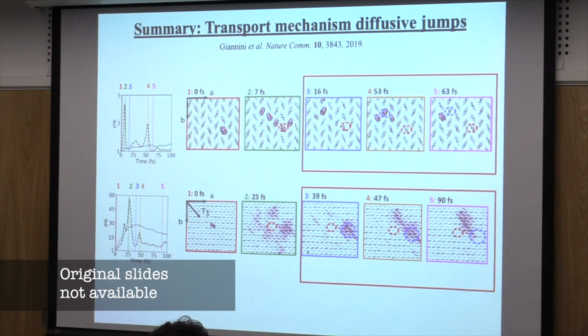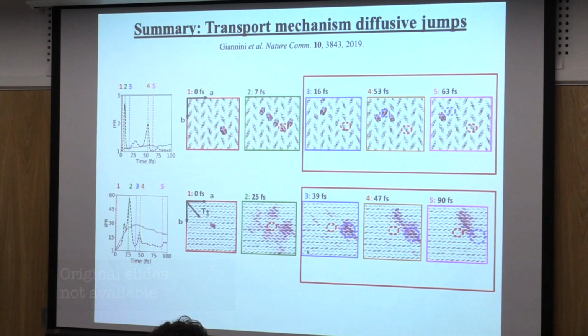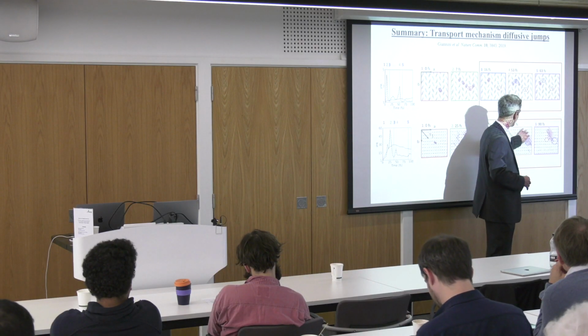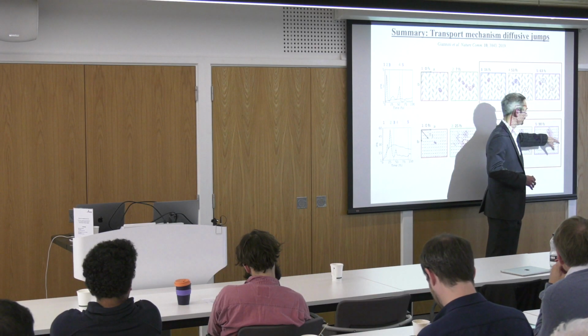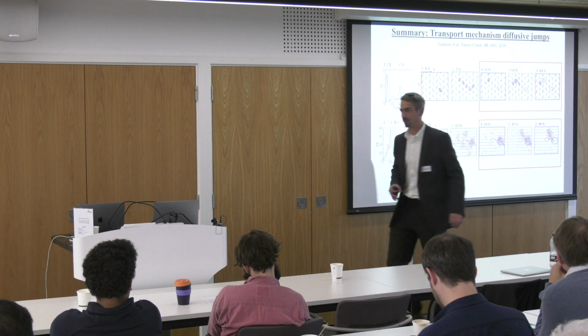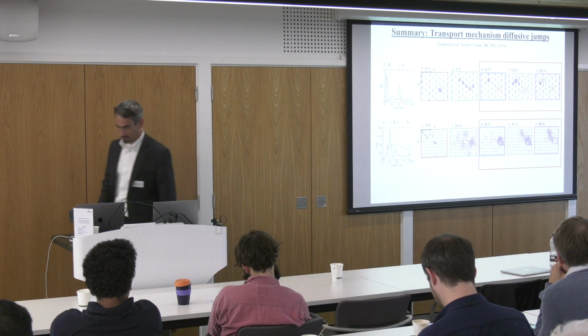This is the normal state. It's the same 20 molecules. At a certain instant of time it expands, delocalizes. It's almost twice its size, and then after a couple of vibrations it collapses to its original size. And this collapse can either be successful or unsuccessful. If it's unsuccessful, it stays where it was. If it's successful, it moves another 5 nanometers along the crystal.